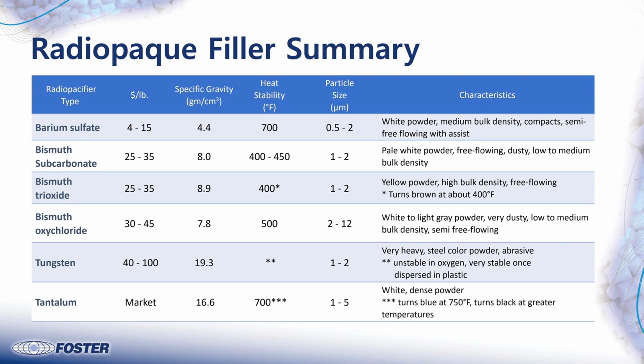And then, certainly the heavyweight champ is the tungsten, very high density. Downside is, you can get black or gray as the color. Very difficult to put a pigment in it because it is a steely gray powder to start off with. You can get very high loadings because it has a high specific gravity. You tend to see this in the tip of a catheter, where you want to really light up the tip of the catheter. Because tungsten tends to degrade a lot of the performance of many of the polymers, especially in high loadings, you might want to limit it to a smaller portion of the catheter. We don't see too many catheters, the entire catheter, that's made with a tungsten compound.